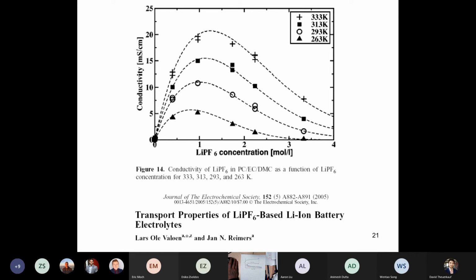And this is a typical graph of electrolyte conductivity as a function of LiPF6 concentration at 4 different temperatures in Kelvin. As temperature increases from 263 to 333, conductivity goes up. And there's this very strange shape, where the conductivity increases almost linearly at low salt content. That's what you expect, because the number of carriers, the number of ions in solution, increases with concentration. But then the conductivity does not continue increasing with concentration, and it rolls over. So long ago, people became interested in trying to understand what the shape of these curves is all about. And I'll discuss that now.